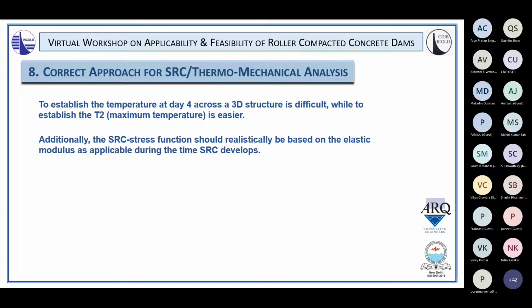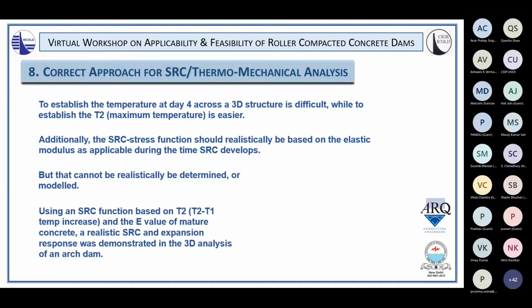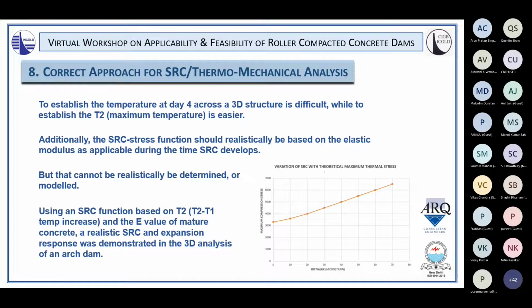Additionally, the function of stress relaxation creep should realistically be based on the elastic modulus as applicable during the time the stress relaxation creep develops. But this is again a very difficult, or not necessarily realistic, thing to be determined or modeled. However, using a stress relaxation creep function that's based on the temperature rise, T2 minus T1, and the mature elastic modulus of the RCC, a realistic stress relaxation creep curve was developed to produce a realistic response within a three-dimensional arch structure. And this demonstrated the nature of the type of stress relaxation creep function that was applicable, basically working with a prototype structure where we understood the response in the different parts of the structure.